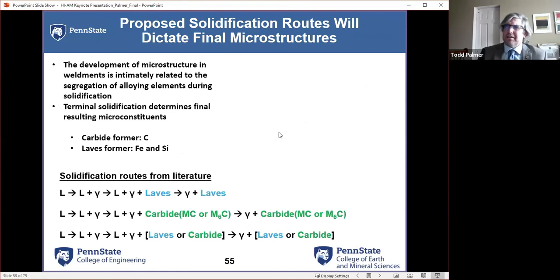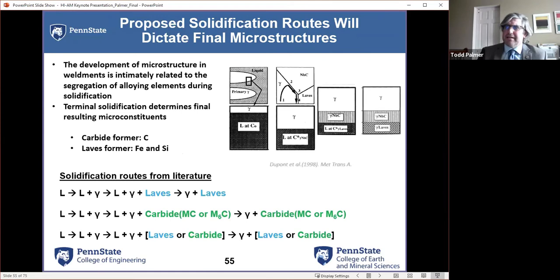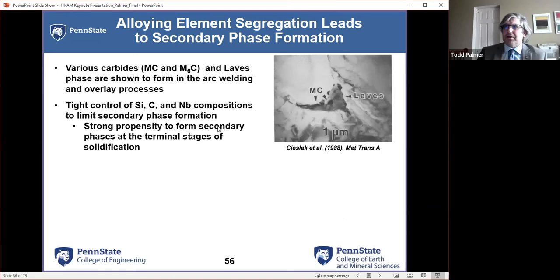Now we started looking at the literature, and when you look at it, this goes back to my old friend John DuPont at Lehigh, who did a lot of great work back in the 90s. So did Mike Cieslak and the guys at Sandia on really looking at solidification modes and starting to understand where Laves phase forms and how when you start welding some of these alloys, some of the issues you run into, whether you have carbide formation or Laves phase formation. And so they did a lot of great work, and they sort of found various in arc welding and overlays, and 625 is widely used across maritime industry for weld overlays. Nuclear industry, it's constantly used in the same type of situation.